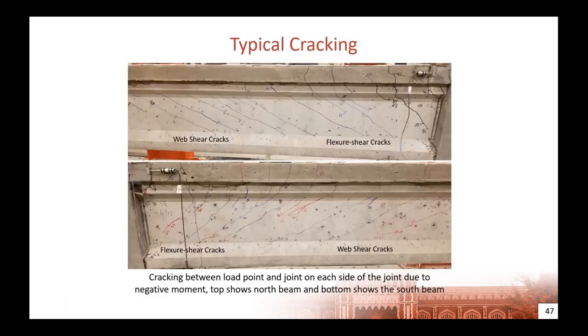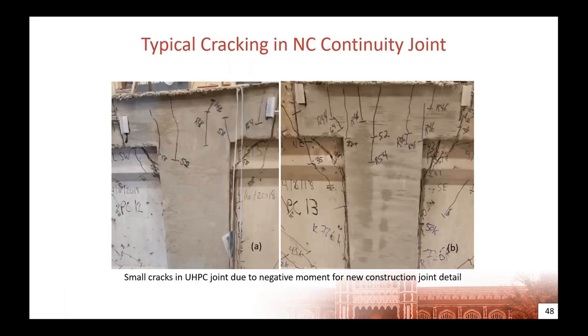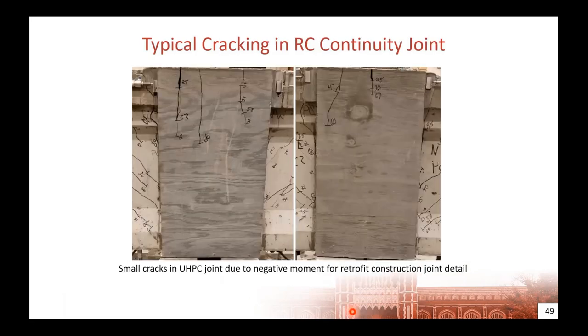If we look at in between the joint and the load point, we would see, again, flexural cracks as we start to move away from the joint that turn into shear cracks, and then some web shear cracks in between due to the joint attracting more shear than we anticipated. Within the continuity joint itself, we would see very fine cracks that for the new construction joint formed at higher loads. We would mark those with a permanent marker, which makes them look larger than they really were. But for the new construction, we saw several cracks that were spread out reasonably well. For the retrofit connection, we saw a few cracks, not as many, but they occurred at lower loads than what we saw for new construction.